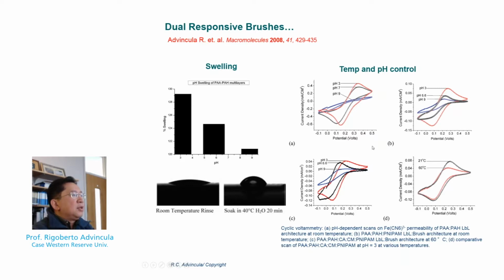We also observe this behavior by looking at the transport of molecular ion probes or electrochemistry by cyclic voltammetry through the surface. Again, by changing the pH and temperature, we can observe changes on the voltammogram, indicating the change in current density versus potential for each of these different conditions.